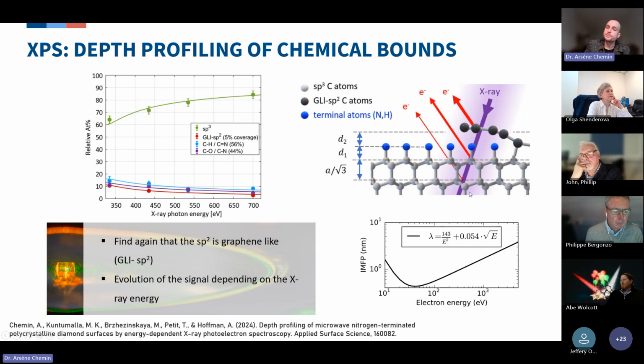So we had the diamond, and then at the surface, we had some nitrogen termination of the diamond surface. And the sp2 that we observed on that surface, we figured out it's actually not surface reconstruction the same way we can have with oxidized diamond, but we were actually able to discriminate it and find out that it is sp2 surface coverage. So basically, the plasma treatment of the diamond will create some carbon waste that would create those kinds of sp2 sheets at the surface of the diamond.